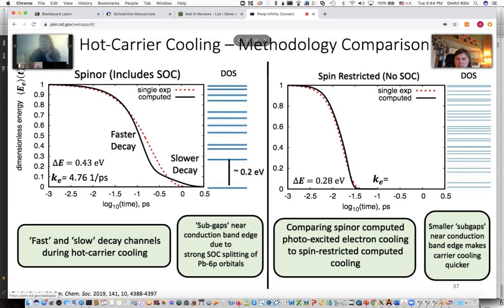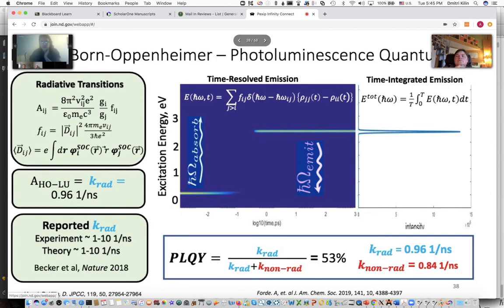But if you compare it to without including spin-orbit coupling on the right, the decay follows a very fast single exponential, and I don't have an exact number at the moment, but it looks like sub-100 femtoseconds, so almost an order of magnitude quicker than when including spin-orbit coupling. If you look at the density of states, this makes sense as well, because without spin-orbit coupling, we don't have those very large subgaps, which help slow down the cooling.